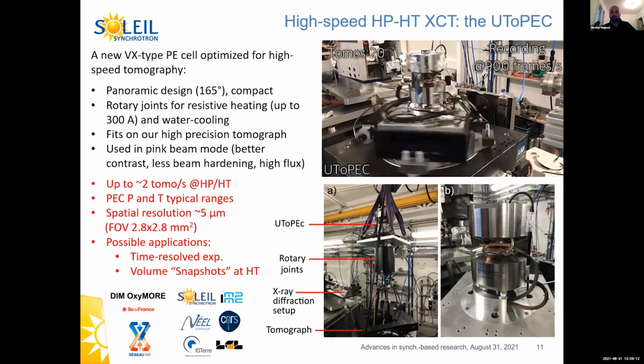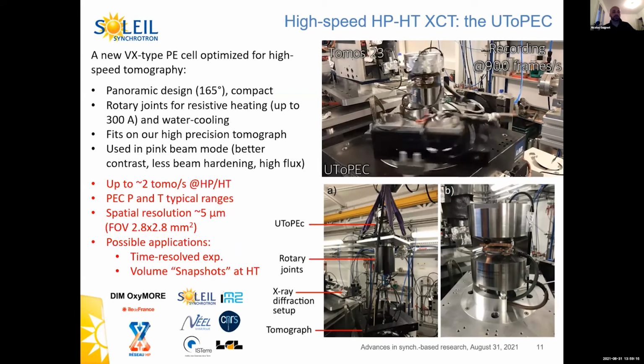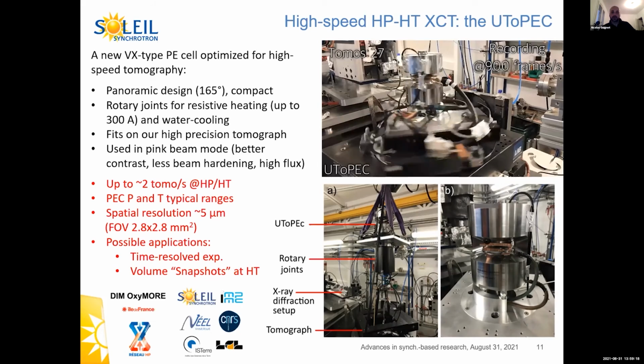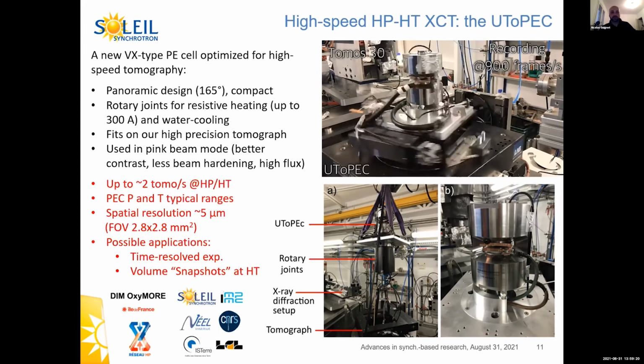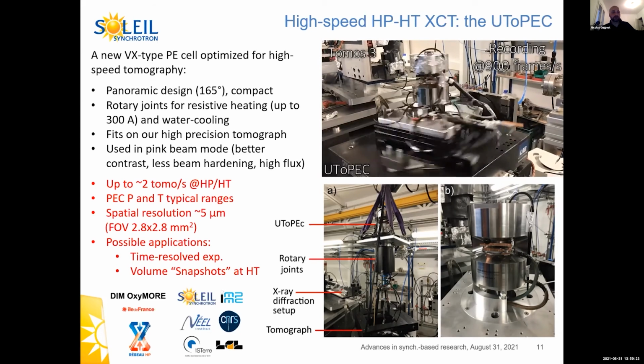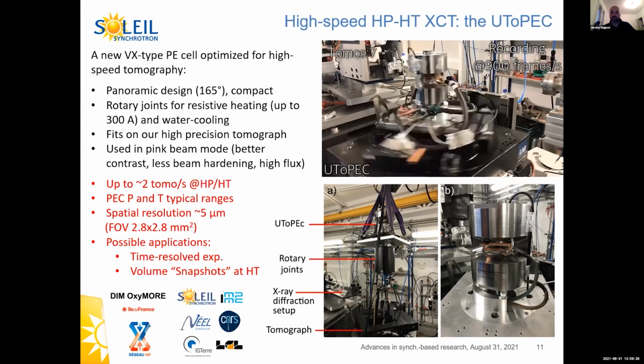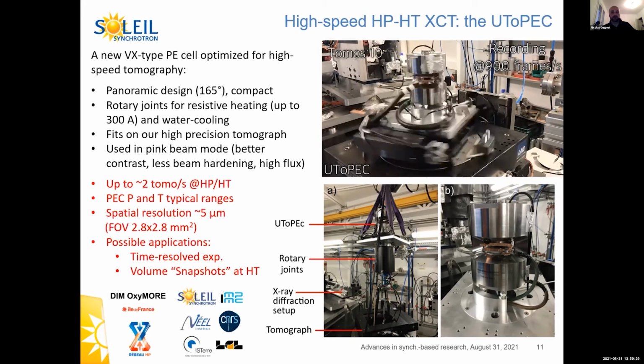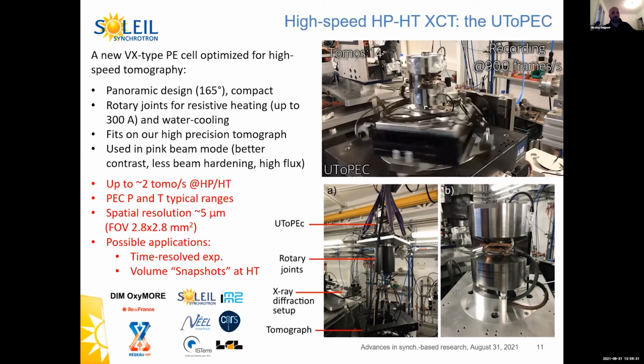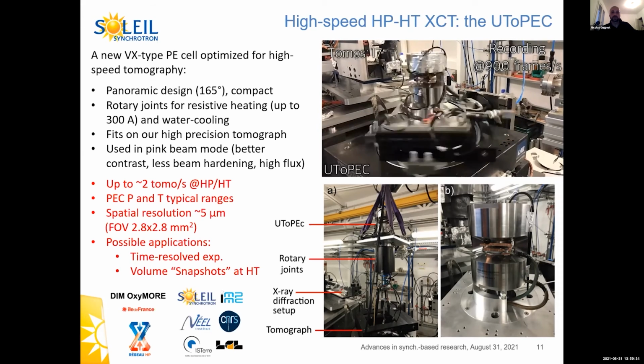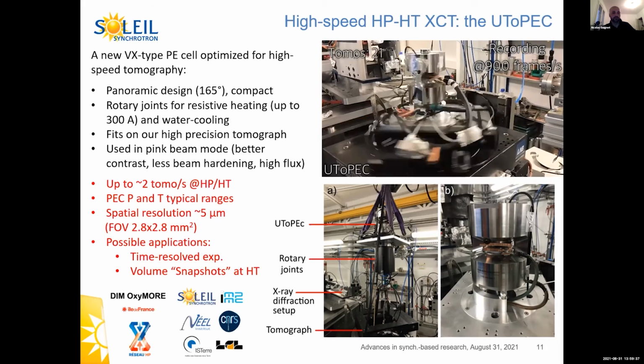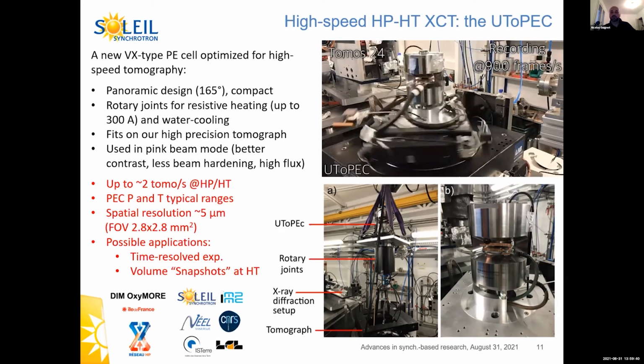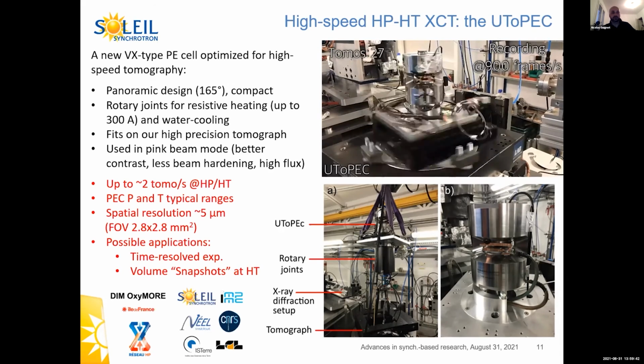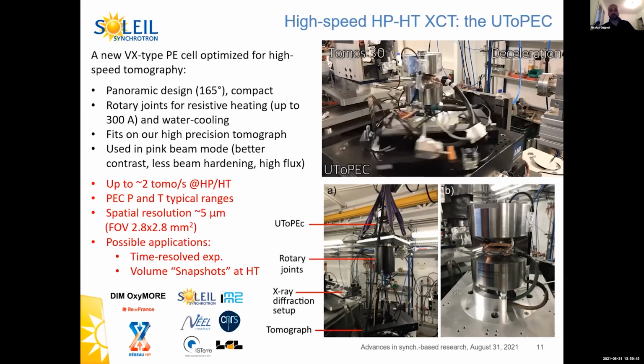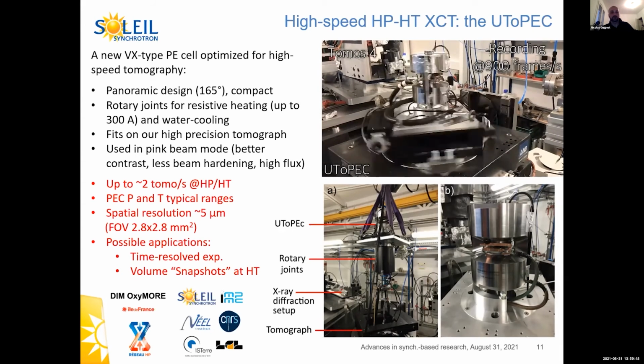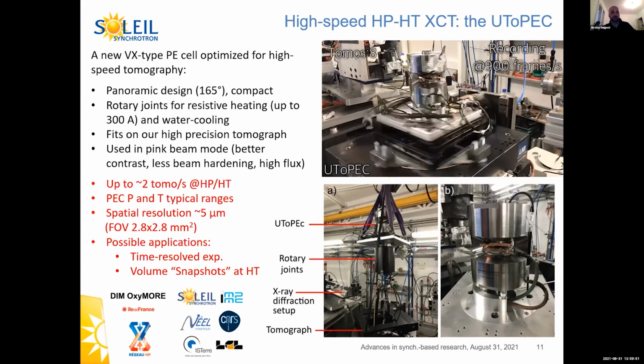It's used in pink beam mode for better contrast, less beam hardening, and high flux. So thanks to the beam flux and the macro tomograph, we can produce up to two tomographs per second at high pressure and high temperature. The pressure and temperature ranges that we can achieve are the typical Paris-Edinburgh cell ranges. The spatial resolution is about 5 microns with a field of view of 2.8 by 2.8 millimeters. So it fits perfectly the sizes of typical large volume loadings.